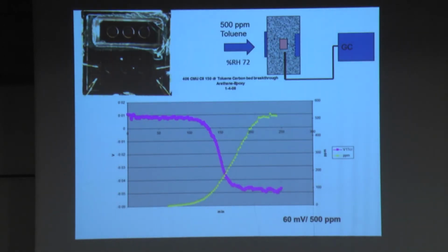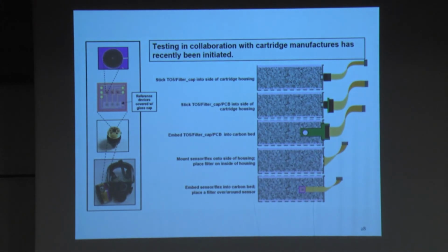And actually, what we saw is that the yellow line is a breakthrough. This is a GC line inserted into the carbon bed, monitoring the actual concentration. And the pink line is the response of one of the sensors. And you can see very nicely, you can easily follow the breakthrough through the carbon. So at this stage, we inserted those devices into several cartridges in different configurations, and sent them to the manufacturers in order for them to fill the carbon so we could test it.